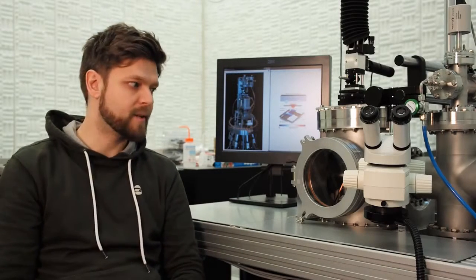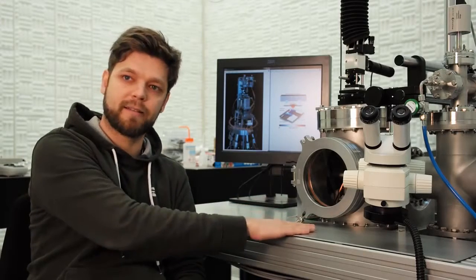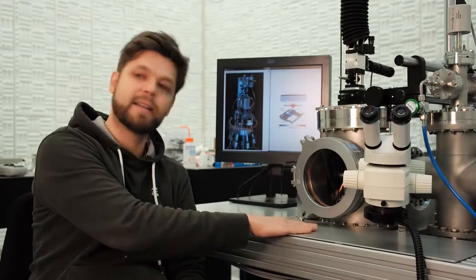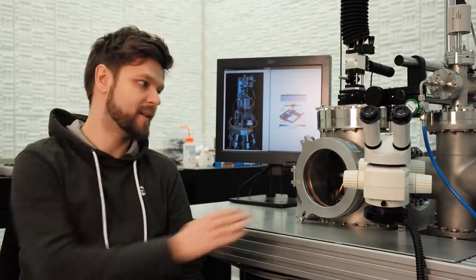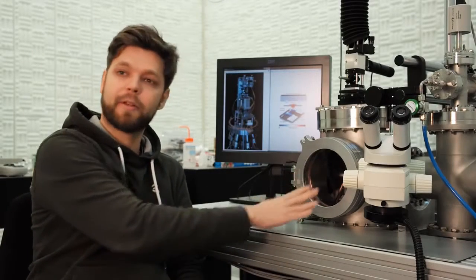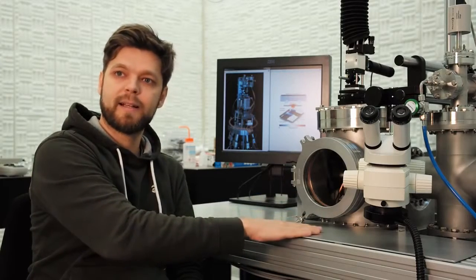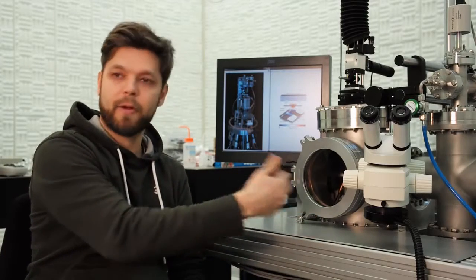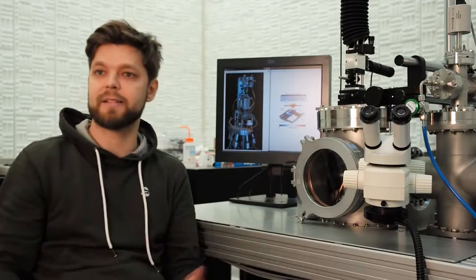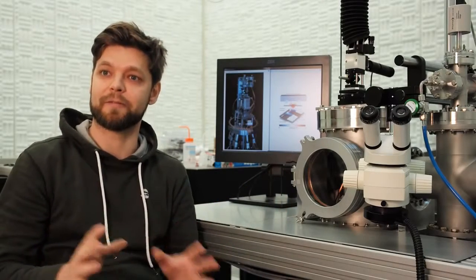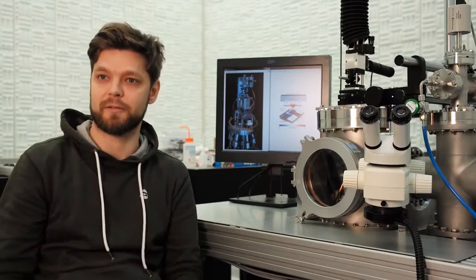Now, the challenge in inferring temperature using this kind of heat flux sensing, as with my hand here, is that it can be very easily misleading. You may, for example, touch materials of different thermal conductivity—let's imagine this glass here, or the metal—and just by the difference in thermal resistance, you may have the impression to touch something of different temperature, which is not actually true.